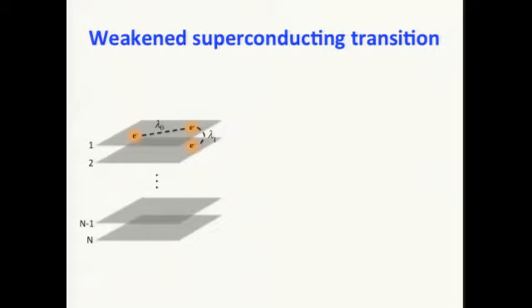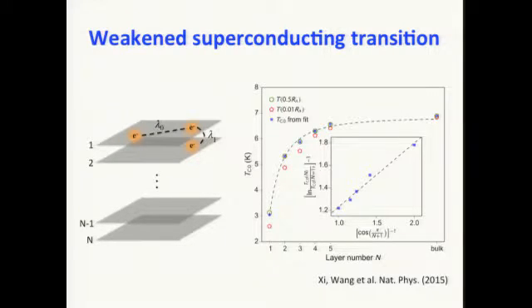And actually, you can put down this model in some mathematical formula, and it turns out that this model, which is represented by this dashed line here, fits the data quite well. This is TC, this is layer number. It basically represents a quite good description to the experimental data.